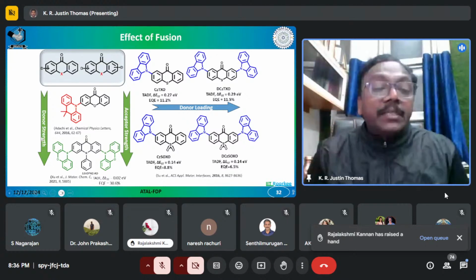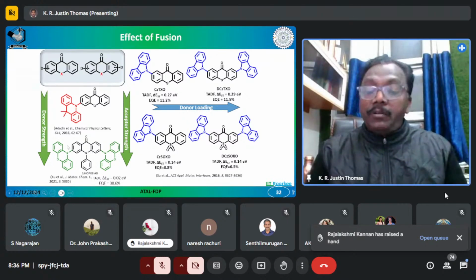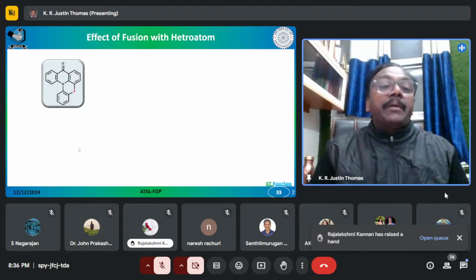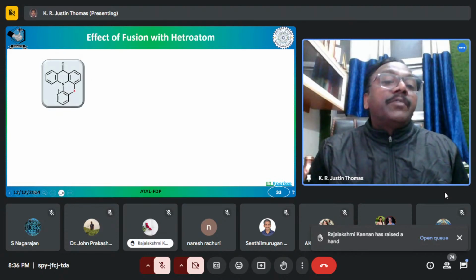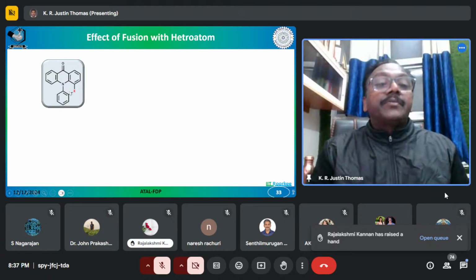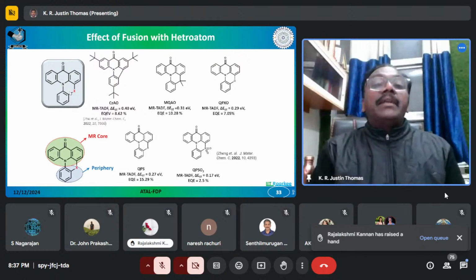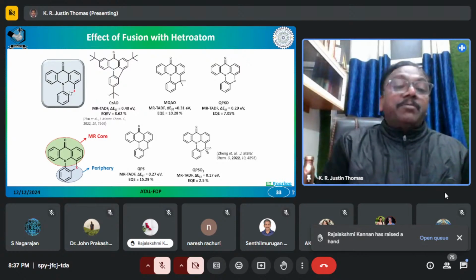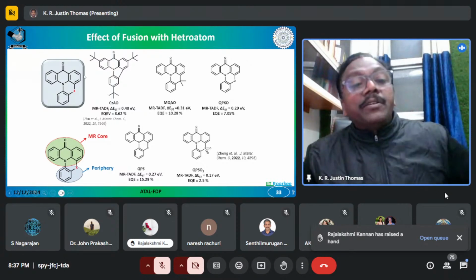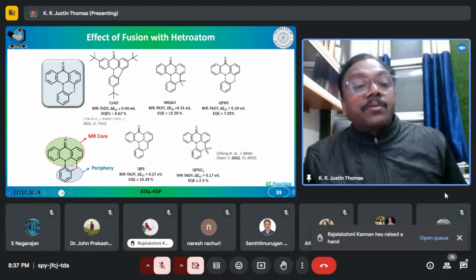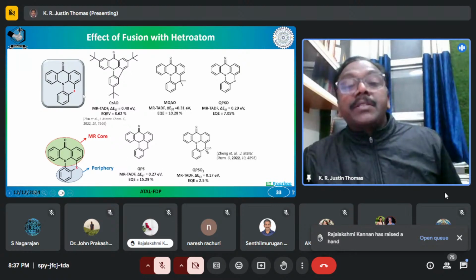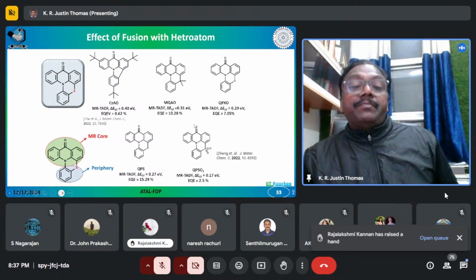So now let's look at this N-phenyl fused molecule, and then do an additional fusion. What happens? With an additional fusion, we will result in this molecule. So now this becomes a multi-resonant TADF molecule. In this molecule, this part becomes a multi-resonant core and this becomes a peripheral core. So now this will also have a lot of implications in the properties. You can see that the delta EST of these molecules is slightly high. However, they are all MR-TADF in nature and show very high efficiency in the LED.